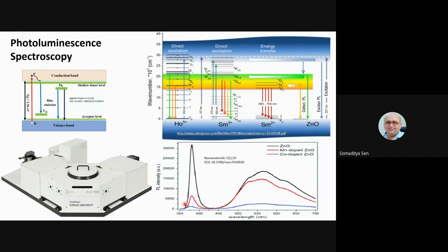Now, when you dope something, that dopant will have some interaction with the neighboring oxygens, so they will determine a different set of energy values. And these energy values in the band diagram will occupy different energy positions, and accordingly you may land up into different types of defect states within the band gap, or in the conduction band maybe, or somewhere else, or in the valence band.